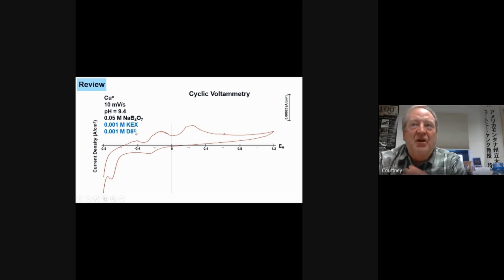And remember, this is charged on both ends, so it's a double anion, divalent. And one, you get your peaks back. You get your hydrogen evolution peak. You get a new peak here. And because we believe it's reacting through the sulfide, the thio group functionality on the D8, we believe it follows what xanthate does. So this molecule chemisorbs and gives up an electron. And then the next peak, we see it kind of responding the same way as xanthate again, where you get surface precipitation, except it's not really surface precipitation.